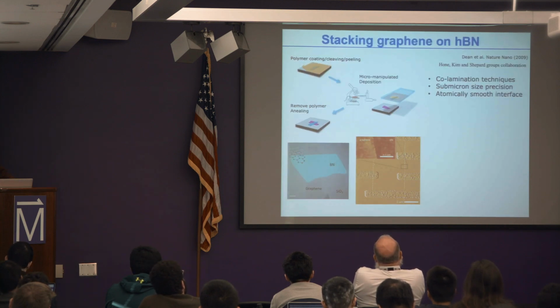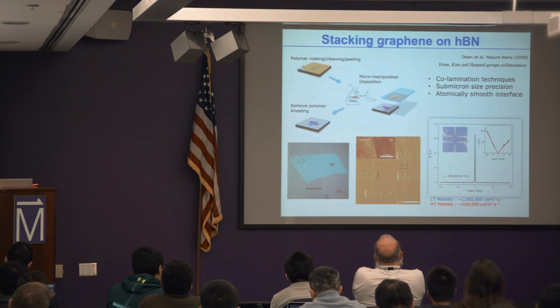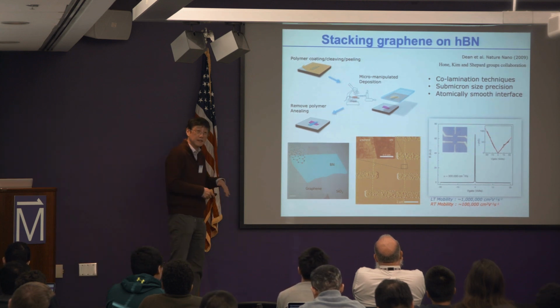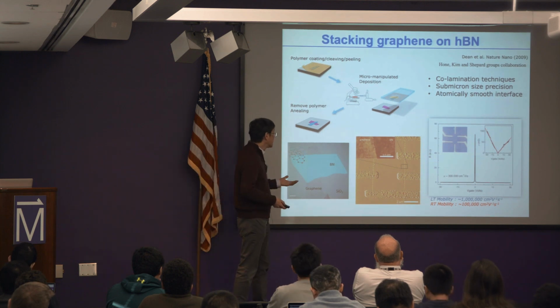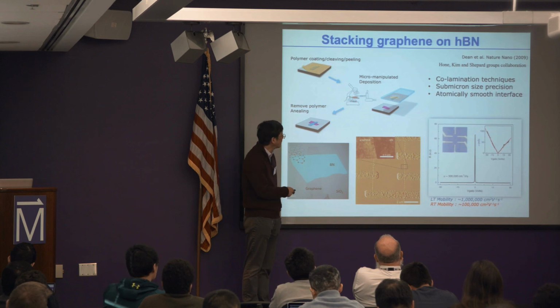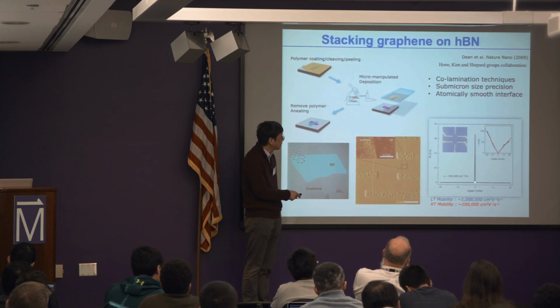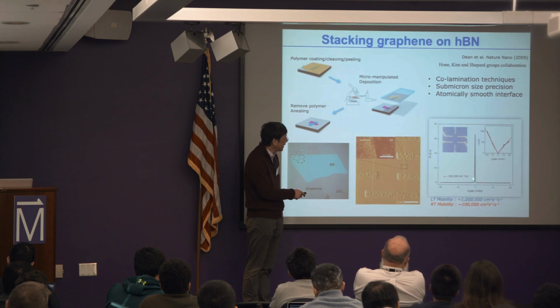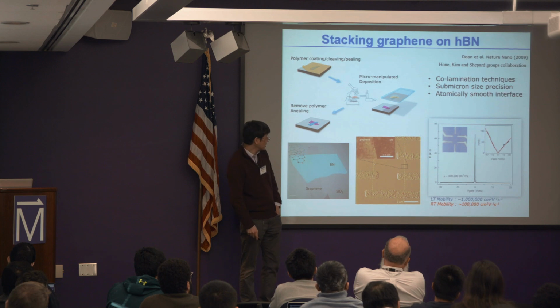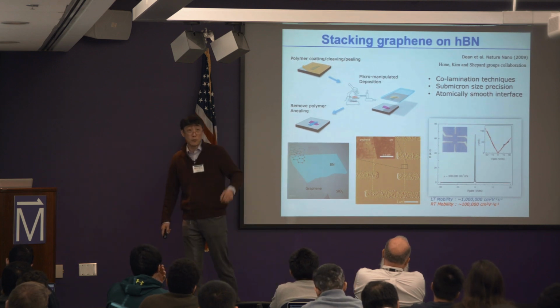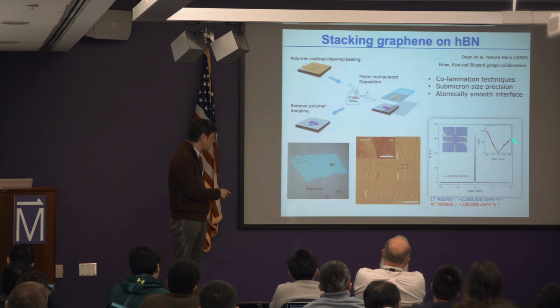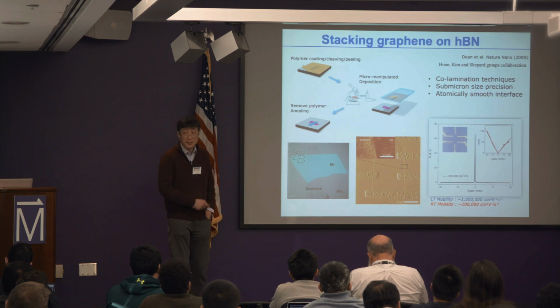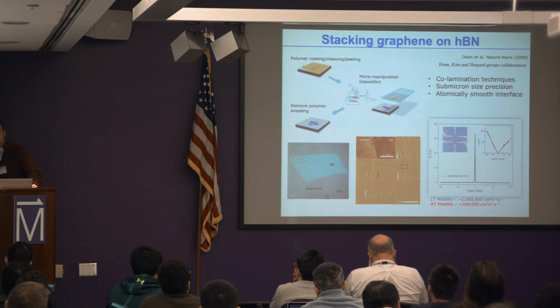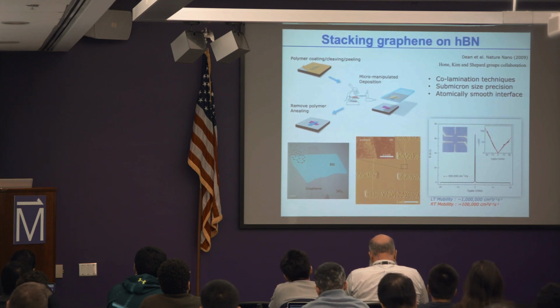Of course, once you create an encapsulated sample, or at least use a boron nitride substrate, one nice thing about boron nitride is that it is a very good crystal, and there are not many dangling bonds or charge traps compared with silicon oxide. So the situation is quite different. For example, for a sample where we put graphene on boron nitride, look at the resistance right at the Dirac point and the dispersion. It is very sharp, right? And the mobility of this sample is about 300,000 centimeter squared per volt-second. That is almost two orders of magnitude improvement over silicon oxide. And this sample is already from the very first generation. After this, there was even more incredible improvement. Now this number is even an order of magnitude larger in the state-of-the-art samples we can achieve.